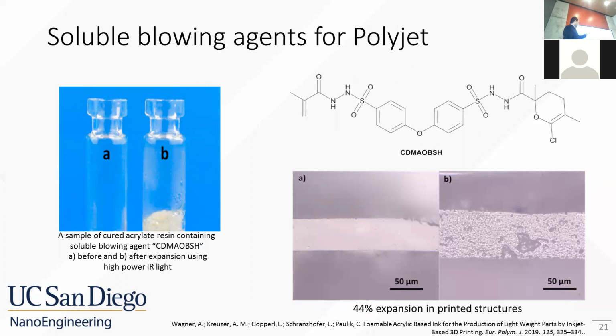Developed a relatively novel hydrazine-based blowing agent, which was soluble in a proprietary acrylate monomer. He was able to print this resin using a polyjet machine, which is a relatively large, very expensive and specialized 3D printing system, and was able to expand it using near infrared light.